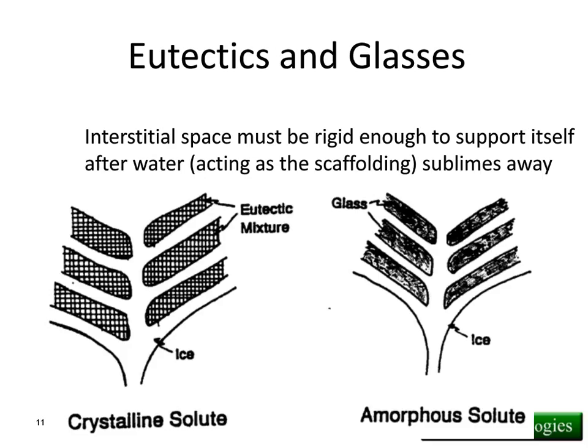And again, just showing you the difference here between the eutectics and glasses. You can see the ice channels, and in between those channels we see the interstitial space. In a eutectic, it's tiny little crystals of ice and tiny little crystals of active or excipient. The glassy phase, we still have the ice channels, but now we've got this really rigid, solid mass. And these trap water very differently. So how we approach primary and or secondary drying is going to be dependent on identifying what we have.